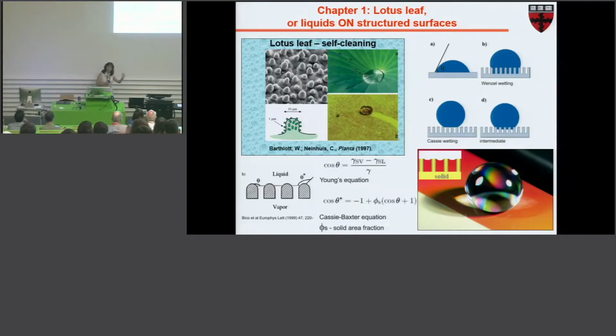If we just talk about chemistry, in particular whether the surface is hydrophilic or hydrophobic, and of course that can be done purely with chemistry, there is a contact angle that describes how the liquid likes the surface. This contact angle for hydrophilic surfaces in interaction with water is less than 90 degrees, this is how they are defined, and higher than 90 degrees for hydrophobic surfaces. What is interesting is that it doesn't matter what kind of chemistry you use, the maximum contact angle you can get for purely hydrophobic surfaces is about 120 degrees. And for the minimum angle, for water that likes your surface, if it's a flat surface based only on chemistry, you won't get below 20 degrees.